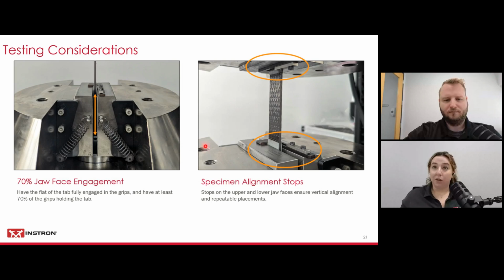Next thing that we like to use pretty often when we're doing composites testing or even metals testing is specimen alignment stops. So these stops on the upper and lower jaw faces ensure vertical alignment and repeatable placements every time. And honestly, it just makes it way easier to load into the grips if you're having to hold the specimen in one hand and then close the grips with your other hand. So it speeds up testing and makes sure that we're vertically aligned properly.